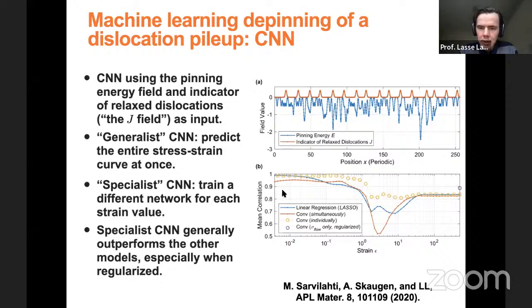So here are some correlations with the stress at a given strain as a function of strain of these different models. So you see that this convolutional model where you do this individual prediction is actually very, very good initially, and it always outperforms the other models. And then you can also fine-tune the model even more. Let's say if we focus on the flow stress here, the last point, then by applying some regularization to this convolutional network, we can actually improve this correlation even further.